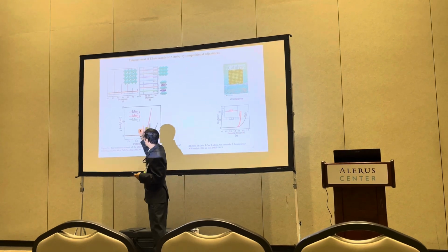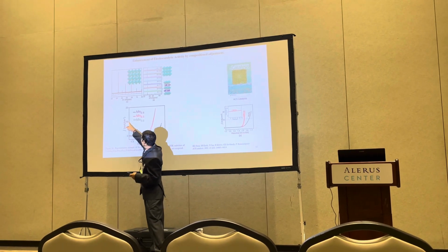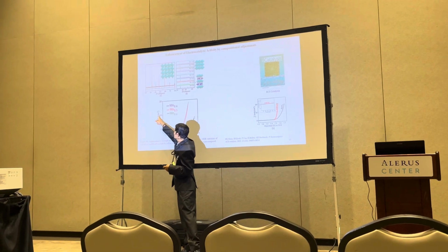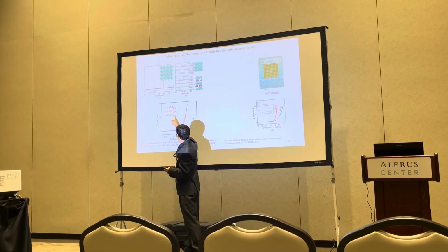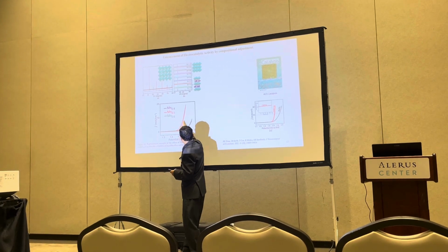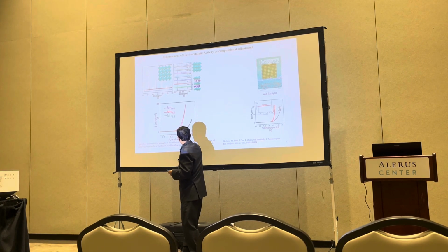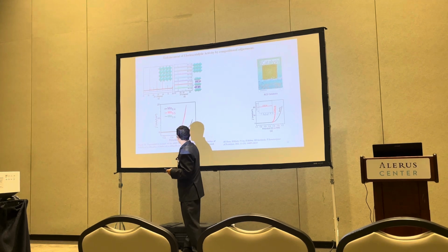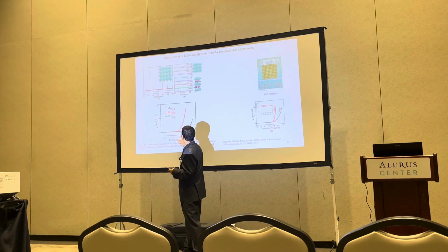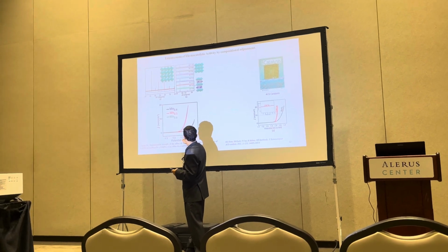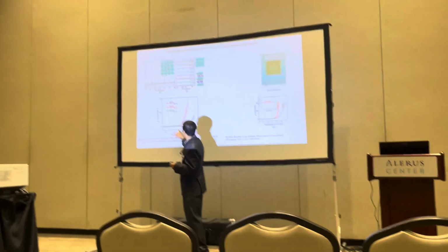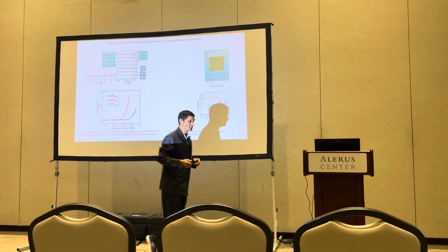Or sometimes it is also measured at 10 milliampere per cm square current density. If we draw a straight line, then we get a straight line here on the x-axis. This is called overpotential. Here it looks like around 1.55, and the lower the number, the better the catalyst.